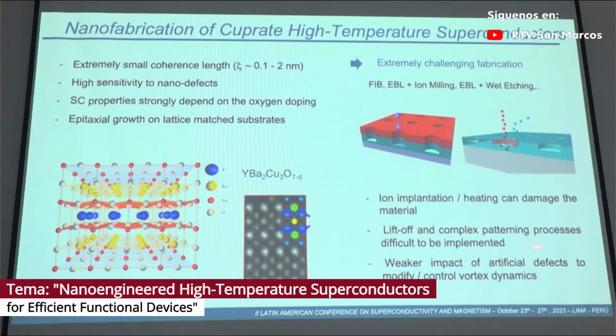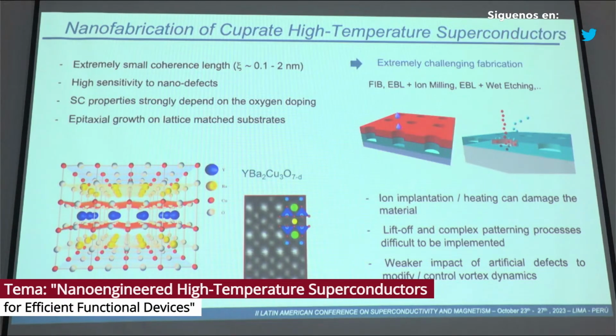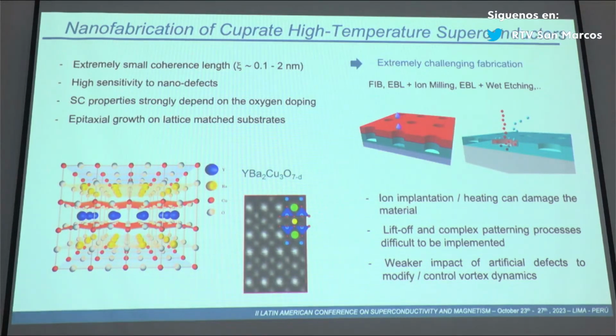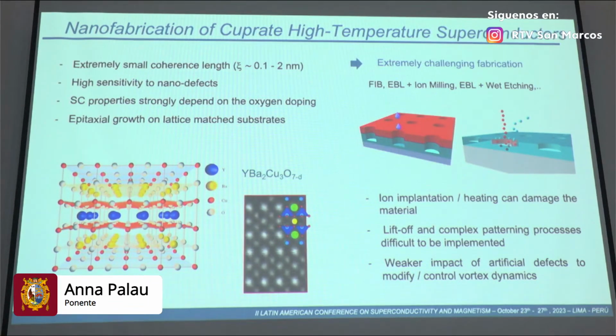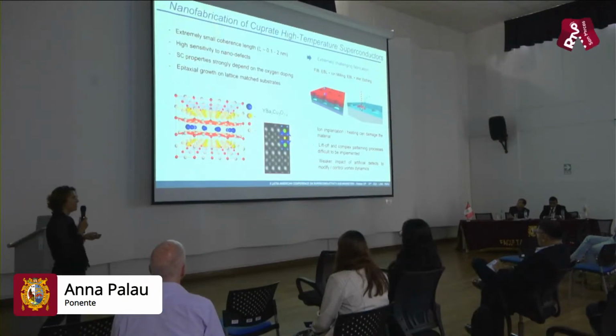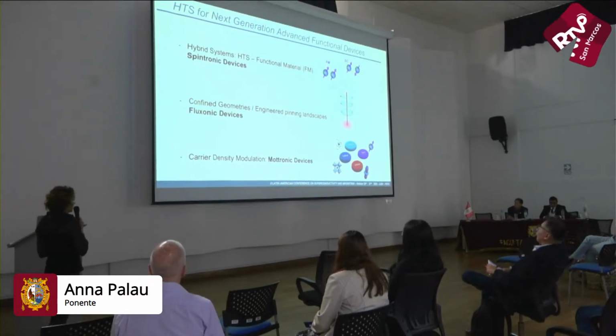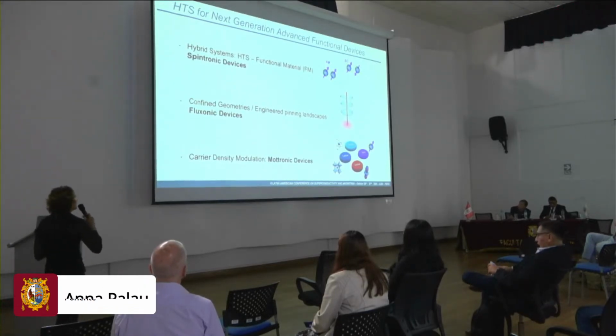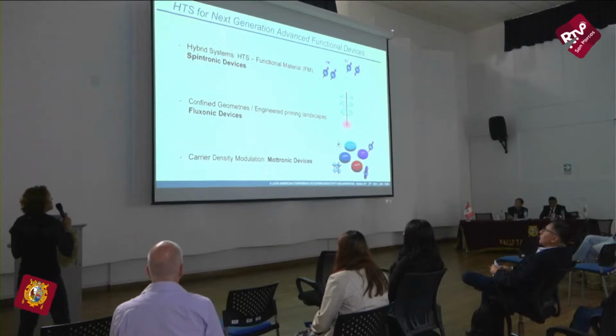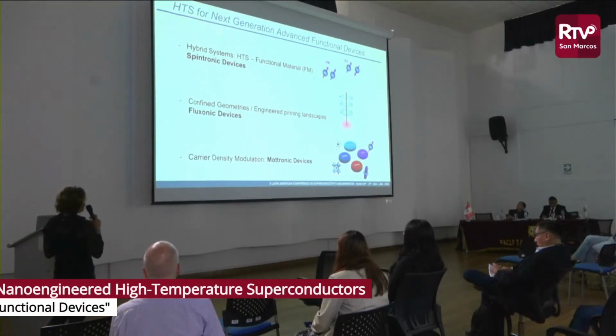Also, lift-off techniques may be complex since we need these special substrates, and sometimes it's not simple. And also one has to think that in these materials we have a lot of defects, and as I said, the presence of defects may affect a lot the properties of the material. So all of these things need to be kept in mind when one wants to work with high TC materials. And what we have done is explore different approaches in order to fabricate these devices.